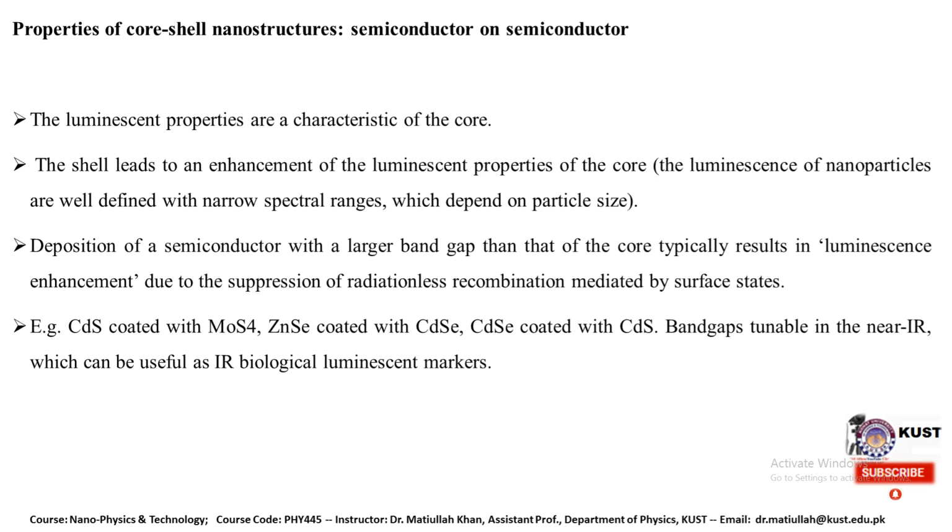So the shell leads to an enhancement of the luminescent property of the core, that is, the luminescence of the nanoparticle, and the luminescence of the nanoparticle is well defined with narrow spectral ranges which depend on the particle size. Deposition of a semiconductor with a larger band gap than that of the core typically results in luminescence enhancement due to the suppression of radiation-less recombination mediated by surface states, and in some cases we will have radiation-less recombination, which depends upon the difference between the energy levels.